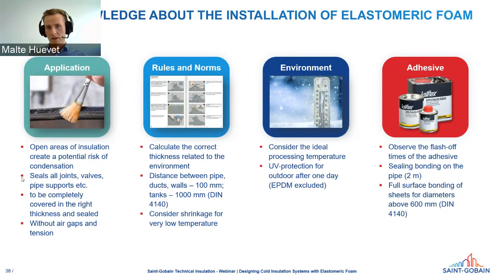But if we want to install a cold insulation, we must always take into account that if there is an open area where the surface temperature will drop below the dew point, then water and condensation will form. So that means we also need to seal every joint, every valve, every pipe support very properly, very tight, and everything needs to be completely sealed. Also, we shouldn't make any big air gaps and also not too much tension. The risk is always there that we get a V-opened joint, for example, or some seams which can go open. And that's also why we don't want to put the insulation on the pipe with any tension.